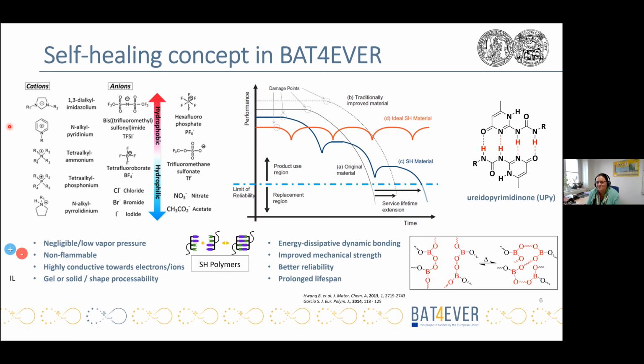Yeah, it's a balance. So we cannot produce a very highly rigid, strong material and at the same time expect it to have self-healing properties, while for self-healing you need at least a little bit of motion of the groups and the polymer chains. So there is kind of a limit of the mechanical integrity which you can reach with the self-healing material. So you cannot have a very highly rigid material with self-healing properties at the same time.